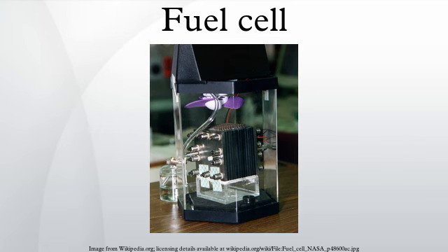Ballard Power Systems has experimented with a catalyst enhanced with carbon silk, which allows a 30% reduction in platinum usage without reduction in performance. Monash University, Melbourne uses PEDOT as a cathode. A 2011 published study documented the first metal-free electrocatalyst using relatively inexpensive doped carbon nanotubes, which are less than 1% the cost of platinum and are of equal or superior performance.